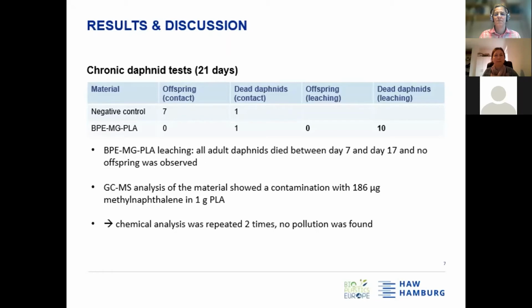And then we found out that 1 liter medium containing 1 gram plastic contained 186 microgram methylnaphthalene. And methylnaphthalene is known as a toxic substance for aquatic organisms and humans. So we didn't have an explanation for the presence of methylnaphthalene in the samples. So we were in close contact to the producers, and they sent us 2 more samples of the material. And in these samples, we didn't find methylnaphthalene. So the question was why the first sample of the material was contaminated with methylnaphthalene.